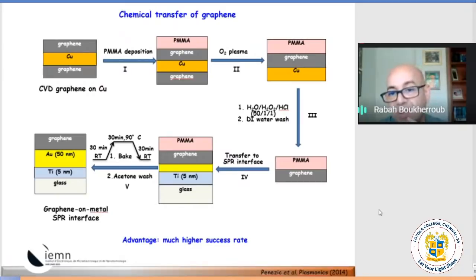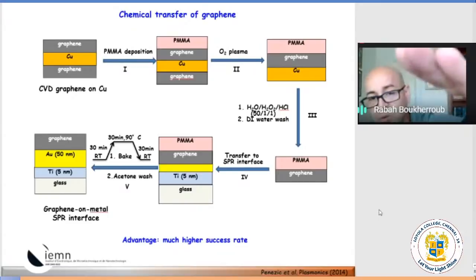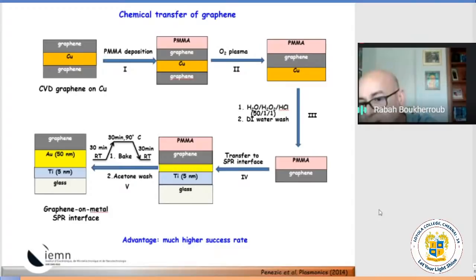So we moved to another technique, mostly used in technology, because you see, you come back, you have the PMMA, which is just a photoresist. The same, you start with graphene on copper. So what you do, you deposit a thick layer of PMMA, a few micron thick, that's not a problem. And you etch the first layer of graphene here, which is on the back of copper. You end up with copper. Again, you etch the copper. It's very easy. You just put it in this mixture of oxidant. You end up with a freestanding graphene, 1 or 2 layers here on PMMA. Then you can transfer exactly the same way to any substrate, with the advantage this time because PMMA can be very easily removed just through acetone washing. And this actually works very nicely. We had a very high success rate and very reproducible.